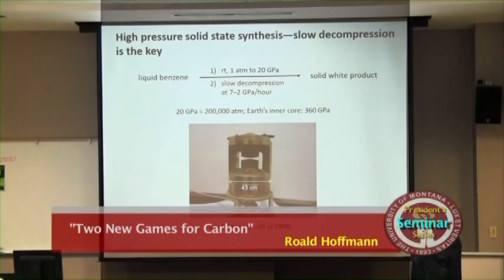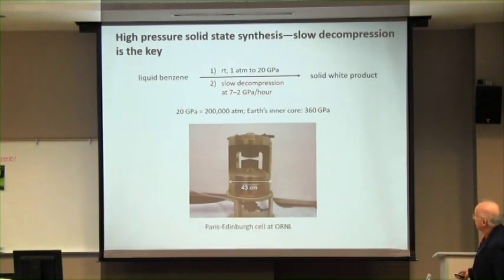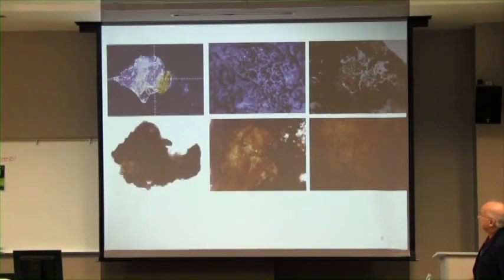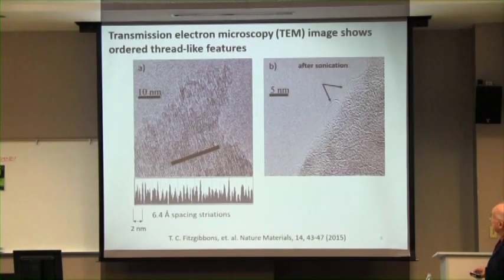They did a slow decompression over 10 hours, which is not terribly slow, and they got occasionally some glassy looking stuff that looks like that. It's still amorphous looking overall, the morphology. Sometimes it was whitish and sort of thread-like, and they decided to look under a transmission electron microscope, and what they saw was this material over here. They saw threads of it, and when they sonicated this to disrupt the structure, they could see the actual little tubules that you see protruding over here.